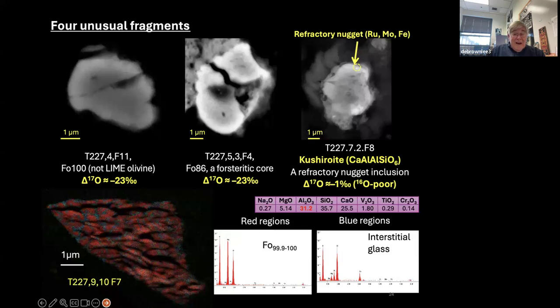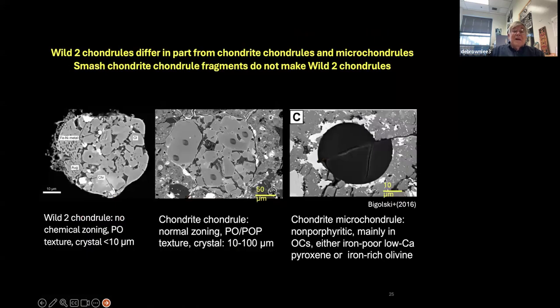On the lower left is an intriguing thing: about FO100 olivine with iron-poor, silica-rich, calcium and aluminum-rich glass in between. Normally this would be considered a crystalline material, but with the TEM we can see that it's not. It's nice olivine crystals with glass in between on an extremely small submicron scale.